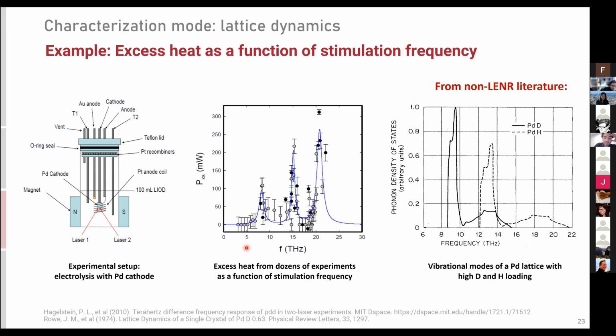And then these people did I think something like 40 or 50 experiments. If you count the points here, you see the number of experiments, and each time they changed the frequency difference between the lasers a little bit. And so in this experiment, there seemed to be certain laser frequencies that give a particularly high amount of excess heat. And so these were later compared with an independent paper which has determined the natural frequencies of the palladium deuterium lattice, and so there was quite some overlap. So that is an indication that prompted people to think that these lattice vibrations might be relevant here.